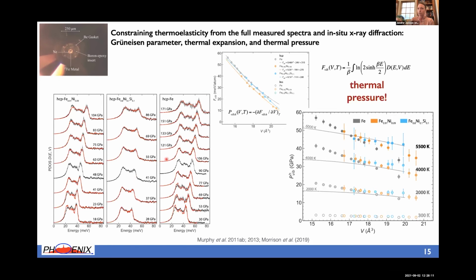And we do see, of course, that thermal pressure is very high from the vibrational component. This is not the electronic component, but the vibrational component can be upwards of 40 to 60 GPa, depending on the temperature. This was also mentioned by Quentin Williams a couple days ago. And so this consideration is necessary for pinpointing where one is making a comparison, for example, of sound velocities and modeling them at Earth's interior conditions and comparing those with seismic observations. At what pressure is one doing those comparisons?